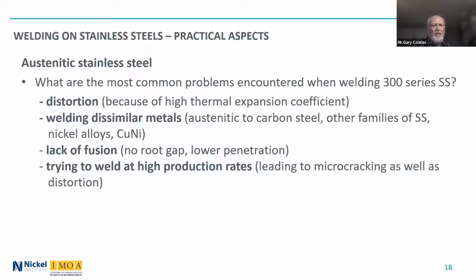And I can't help but include trying to weld at high production rates. Everybody wants to weld more, so you turn up the amperage on your machine and try to do it faster, and that can lead to micro cracking and distortion and a lot of repair welds. So you actually weld faster, you fill the joint faster, but then you have a lot more work afterwards.